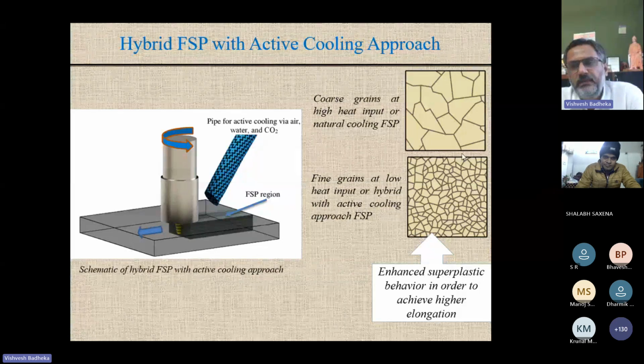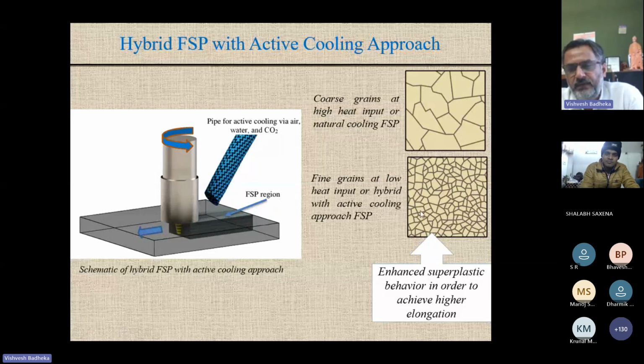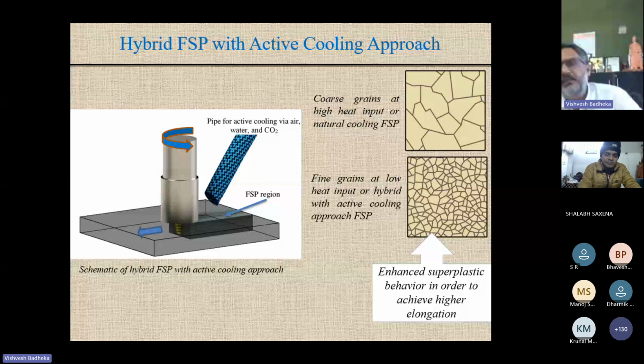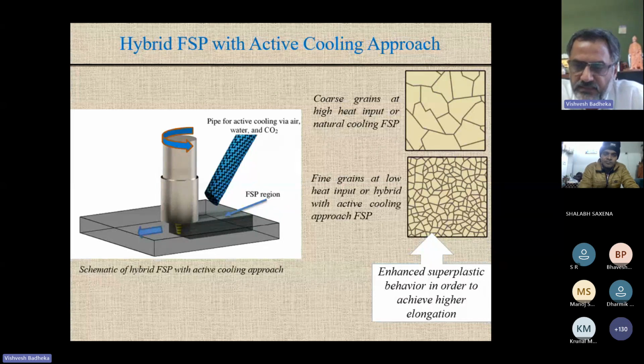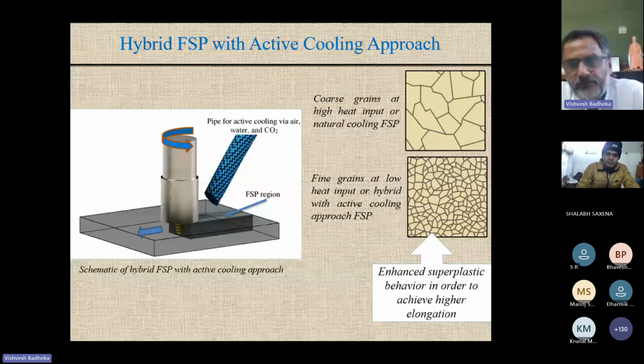And you can see here, this is the coarse grain structure that you have initially, right? And after the FSP, you can see the coarse grain become fine grain. So this is one of the requirements. It should be less than 15 micron. At the same time, they are uniformly distributed, right? The third, you have high angle grain boundaries. Fourth, the precipitates also should be uniformly distributed. So this behavior may lead to a higher elongation in the material. And this behavior is termed as superplastic behavior in the material.